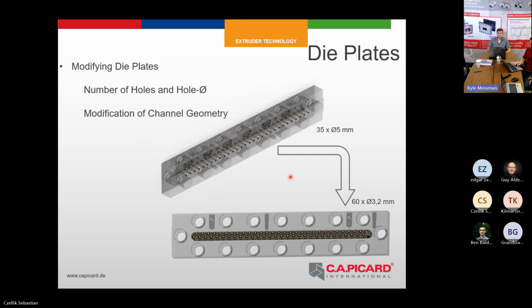The challenge here was that we could not put 60 holes in a row, because they are too narrow to each other. If you can imagine, if we press the polymers through the holes, they would glue to each other, and you cannot cut the polymer into granulates anymore. So we decided to make a 2-row design to gain more space between the holes, and the 60 single strands go to this granulator and could be cut fine into the granulates.